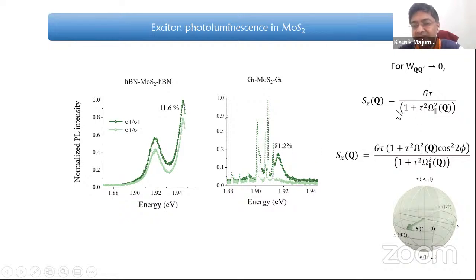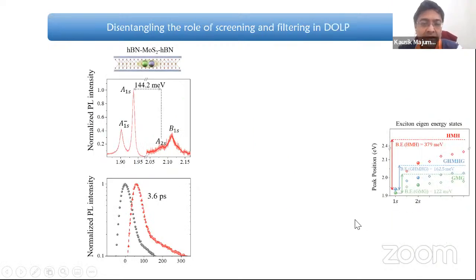The reason is that, because the pseudomagnetic field is in plane, it's easier to maintain the valley coherence with linearly polarized light, because your pseudospin is also in the same plane. However, in the circular polarization case, the pseudospin is pointing out of plane, so you have a strong component for the first term, and that degrades circular polarization more rapidly. Okay, all right. So anyway, we wanted to understand this further.